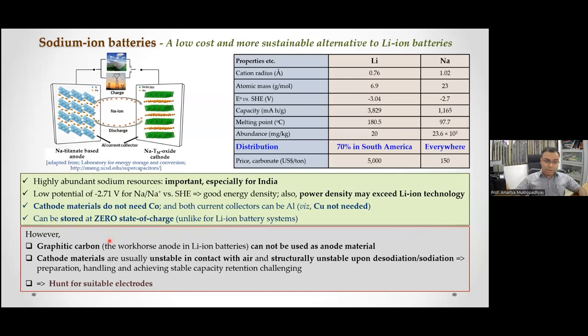And because the handling and storage becomes an issue, one would think that it may not be possible to use water to prepare a cathode slurry if one is using a layered transition metal oxide-based cathode material for sodium ion battery. So that is one. The second is that compared to the lithium transition metal oxides, like the lithium NMCs, the layered sodium transition metal oxides are also unstable upon electrochemical desodiation and sodiation, that is during the charge and the discharge. And so the stability of the structure suffers, and so the electrochemical cyclic stability. So these are the challenges. But again, because these are the challenges, we have some work to do, and we try our best to understand the basic causes of these challenges and figure out a way from the scientific perspective how to address them and then take it forward.